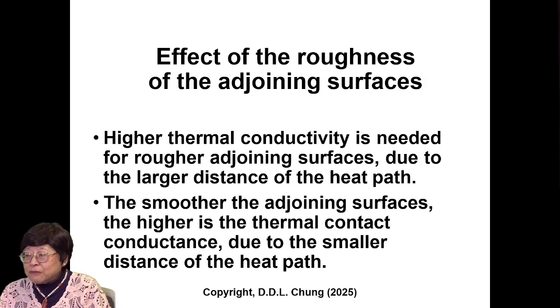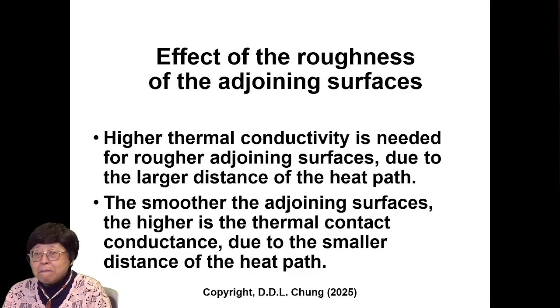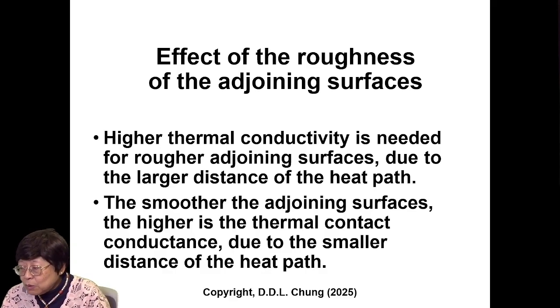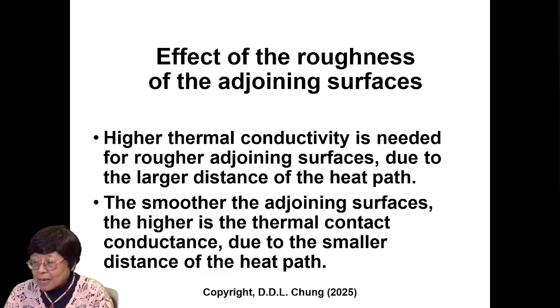Now, the roughness of the adjoining surfaces matters a lot. Higher thermal conductivity is needed for rougher adjoining surfaces due to the larger distance of the heat path. The smoother the adjoining surfaces, the higher is the thermal contact conductance due to the smaller distance of the heat path. So it'd be better to polish your material to make it as smooth as possible.